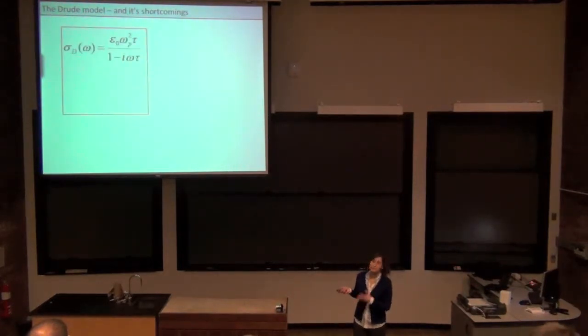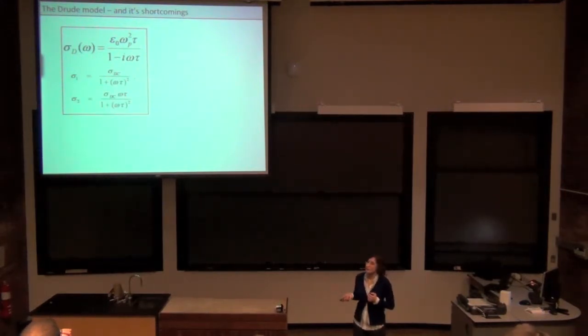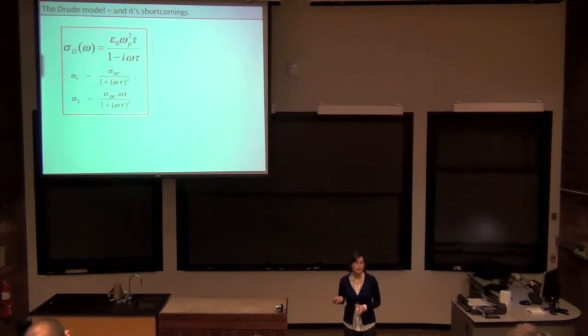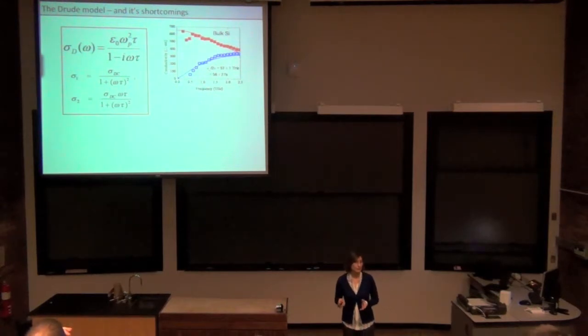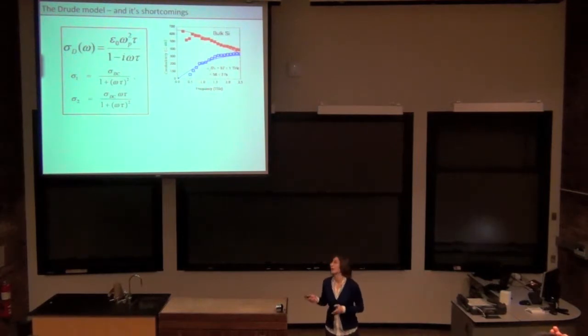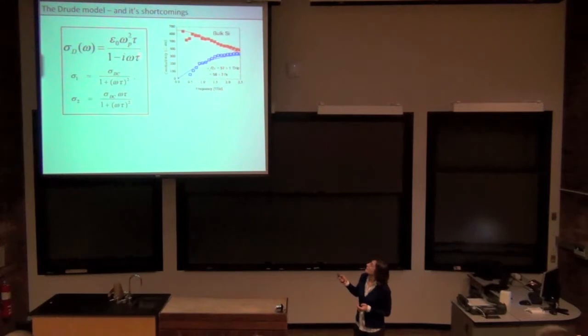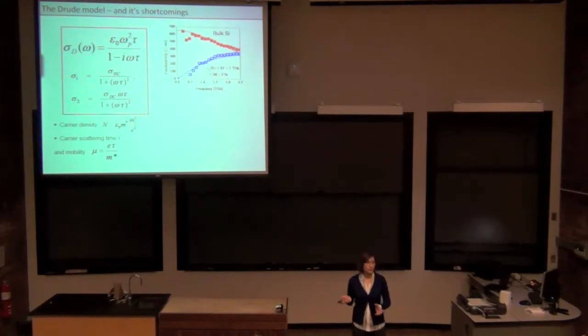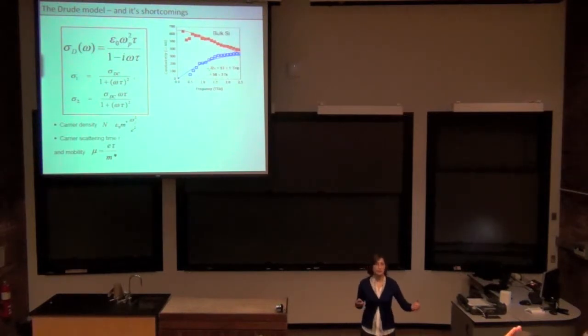What you get is this formula for the complex conductivity, and if you actually write it out, this is your real part, this is your imaginary part. It turns out, for all the simplicity of this model, it works amazingly well. It pretty much describes most of your bulk semiconductor materials very well. From it there are two fitting parameters. One is the plasma frequency, which directly gives you the carrier density at that time after photoexcitation. The other parameter is tau, which is the scattering time, from which you get the mobility of the carrier. So you get all this very important information without needing any contacts. Just come in with an optical pulse and you get the spectrum.